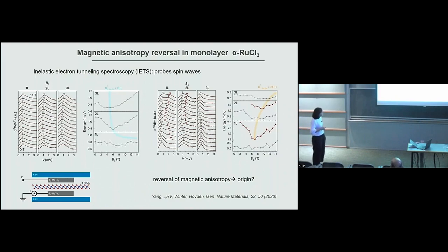In the 2-layer system, this behavior seems to be similar, but at a larger field. In the purely 1-layer, it seems that the system stays in the ordered phase, even at 14 Tesla.